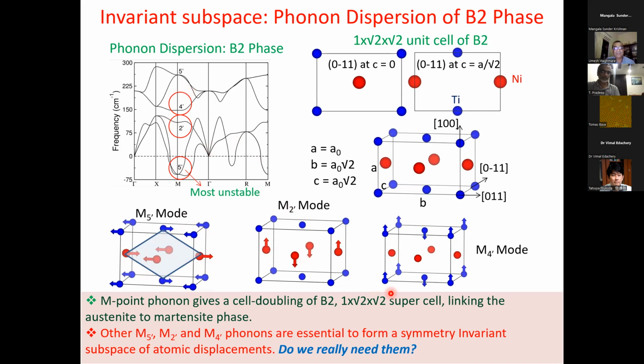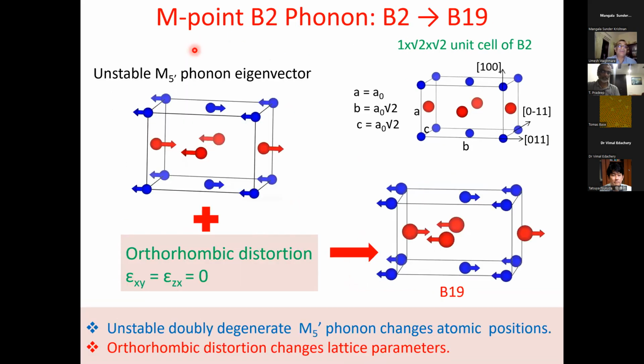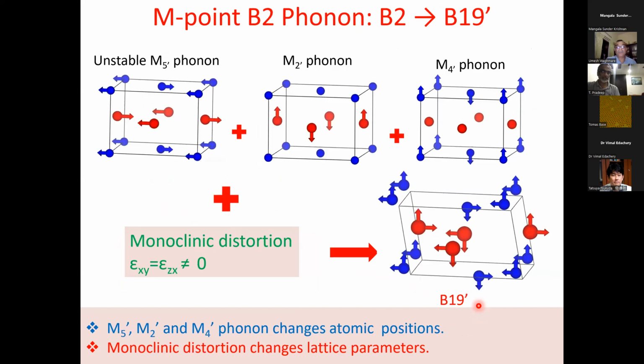And then there's other phonons, and natural question is, are they important? If there's only these phonons which are unstable, do we really need to worry about these other modes in the system? And what we find is, unfortunately, yes, this is fairly complicated phase transition, and we have to include all of these phonons, because if you include only the unstable phonon, you get orthorhombic phase at low temperature, B19 phase, which is not the martensitic phase in nickel titanium. So only if you include combination of 3 distinct phonons, some of them are stable phonons, called the secondary order parameters of the phase transition, and include monoclinic distortion, you can get the right symmetry of the martensitic phase.